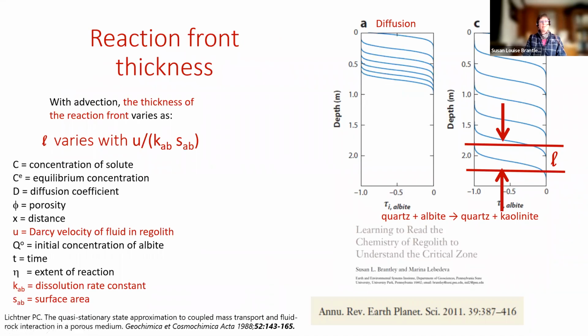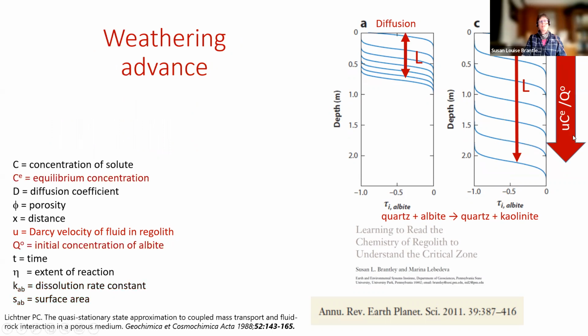So it turns out that this reaction front, we see these all around us, and they have a lot of information, and these are patterns that we can start to learn to read really easily. It turns out that at least in the models, the reaction front thickness is a function of how much advection goes through the system divided by the rate constant. So it's the ratio of transport to reaction. And the depth you can think of as the advection velocity times the solubility. So that's the total amount that can be removed per packet of fluid divided by however much albite there was in the system. So there's a lot of information there.